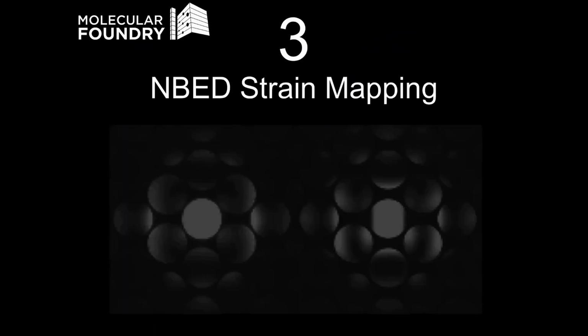So this is typically referred to in the literature as nanobeam electron diffraction strain mapping, NBED. And for this type of data set, we want to set the probe size, the probe semi-angle, so that none of the disks overlap, like the two images I'm showing below there. Because if the disks don't overlap, you can measure their position with very high precision. And slight subpixel shifts of the disk can be used to measure strains even significantly below 1%. So strain mapping is very important for many different studies.